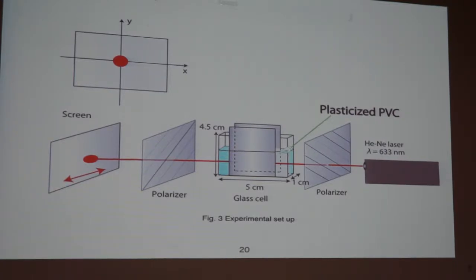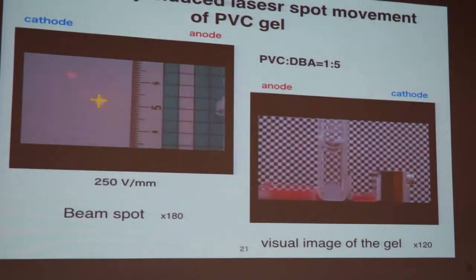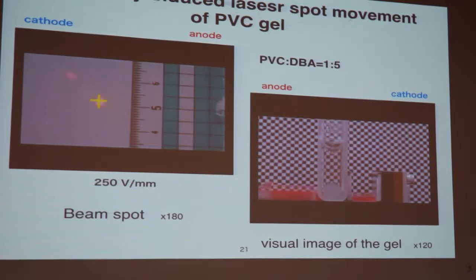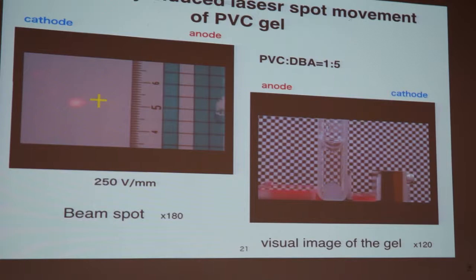This is usually employed for electro-optical function measurement. And this is the data. When we apply an electric field to the gel, deformation and large deflection are observed, in this case, like this. Very efficiently, the light beam was shifted, in this case, to the cathode side. And this is the visual image. When we apply an electric field, you can see some distortion of the image on the surface. So this is what we can induce by applying an electric field to the gel.